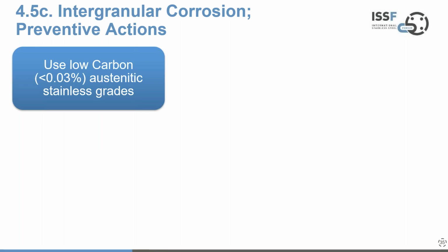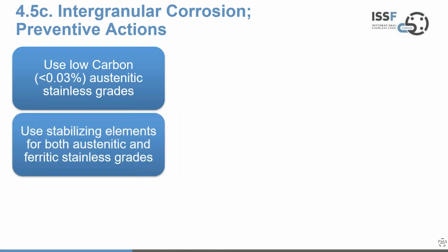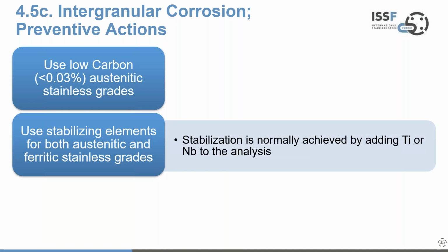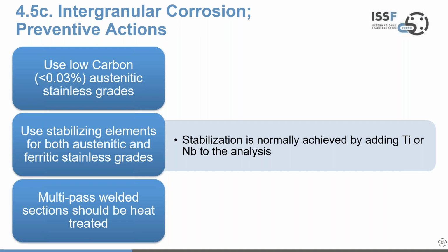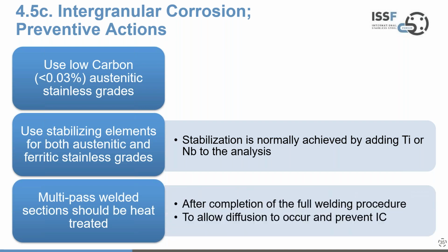So what do we do to prevent this? Well, first and foremost, use low carbon, that's less than 0.03% austenitic stainless steel. So there isn't the carbon around to mop up the chromium when you're undertaking welding and things like that. If you can't achieve that, or that's the wrong type of grade, then use stabilizing elements for both austenitic and ferritic stainless steels. And this is titanium or niobium being the most common, because they will preferentially combine with carbon at these elevated temperatures. And remember that if you're undertaking multi-pass welding, they should be heat treated at the end. This will allow diffusion of those carbides to occur. So 3 very simple thoughts there to prevent intergranular corrosion.